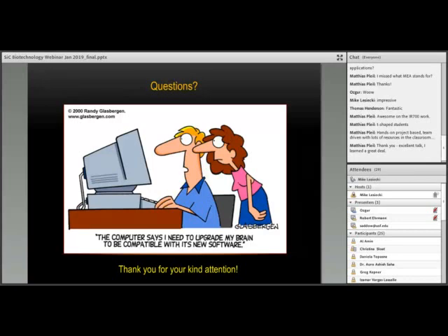That's a very good question. We've never come across that because, again, we have evidence that silicon carbide nanoparticles are also highly biocompatible. But again, at the nanoscale, those are tough challenges. The fact that cubic silicon carbide nanoparticles were ingested into cells and shown to fluoresce is quite encouraging. So you can imagine if these cells had been poisoned by these nanoparticles, they would be dead, right? There would not have been a cell body left. So they lived and they went through their life cycle without any problem. But yes, that would have to be more exhaustively studied.